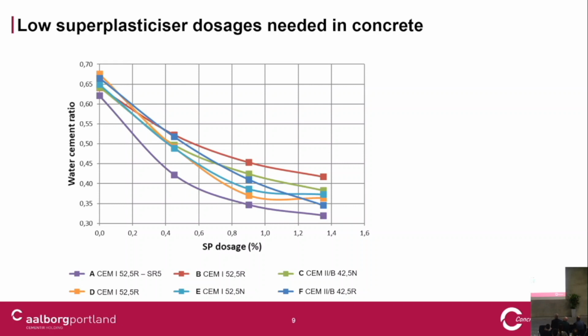But you see, these are different concretes, but with the same flow, the same consistency. So all the points here represent a concrete with the same flow spread. If you have no superplasticizer, you need a lot of water, a high water-cement ratio, to have a concrete with a certain flow spread. Putting in superplasticizer, you can reduce the water and still have the same flow spread.